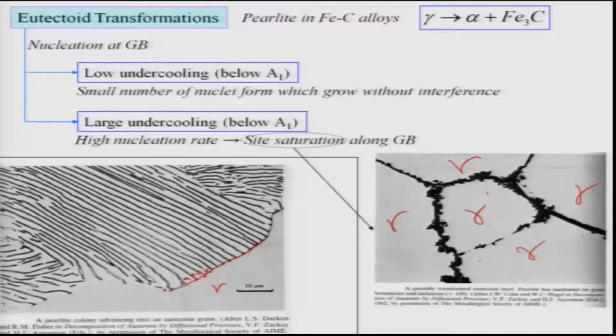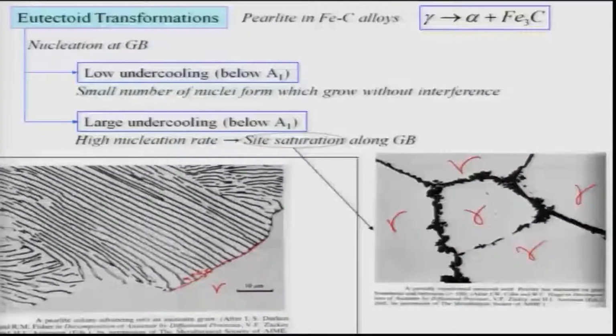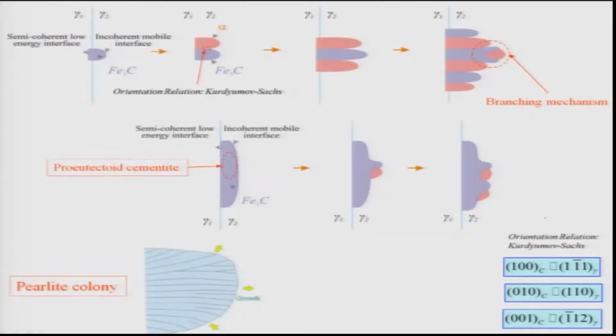Now, once the nucleation happens, it can happen for either of these two phases, alpha or Fe3C. Both can nucleate side by side, or they can nucleate separately. Mostly it has been seen that for the hypoeutectoid alloys, the alloys containing less than about 0.8% carbon, nucleation normally happens for the alpha phase. On the other hand, for the hypereutectoid alloys, it mostly starts with Fe3C. Whatever the situation, the transformation process does not change much. Okay, let me tell you how it happens.